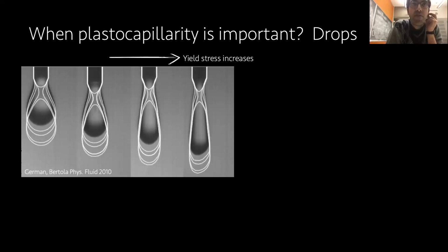I got this picture from the lab of Wolfgang Bertola. What is shown here is a droplet dripping off a nozzle, and from left to right, the yield stress of the material is increasing. We know for Newtonian fluids, this problem shows the Rayleigh-Plateau instability, the pinch-off and droplet formation. But you can clearly see that with yield stress materials, as you increase it, the droplet becomes elongated. So the shape of this droplet is the result of a competition between surface tension, which wants to make the droplet spherical, and the yield stress that resists such a deformation.